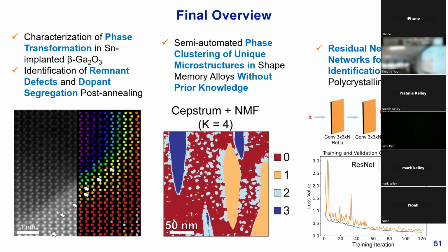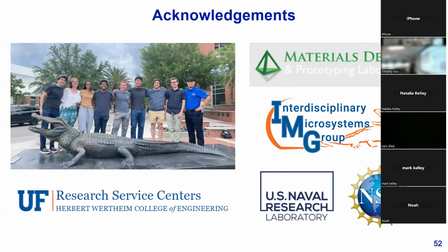And so in summary, what we saw throughout this whole talk today was that we were able to characterize phase transformation in tin-implanted gallium oxide, as well as the identification of remnant defects and dopant segregation using atomic scale imaging and digital image processing. We then expanded our field of view towards shape memory alloys, where we were able to use semi-automated phase clustering of unique microstructures without necessarily having prior knowledge of all the structures that were present. And then we also saw how residual neural networks had very good performance in terms of phase identification in polycrystalline systems.